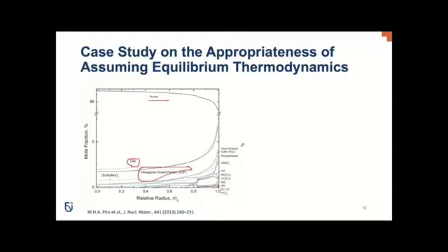We're under different conditions, like for fast reactors with MOX fuel. But you can notice that the models predict a number of other phases to precipitate in this fuel, and that is not experimentally observed. So that's one area where the assumption of equilibrium thermodynamics kind of breaks down.